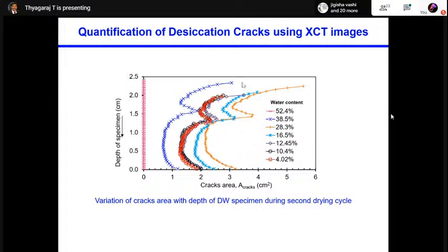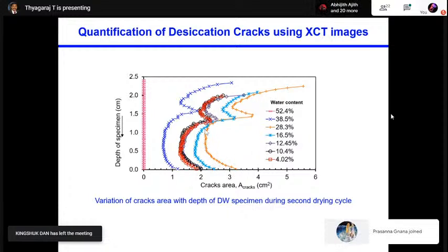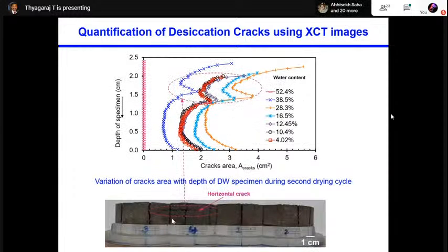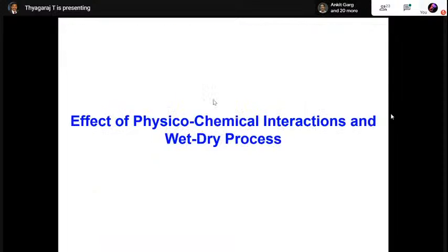Further, you can see that with the depth variation, at the surface cracks were more and at the bottom cracks were more, but in the middle portion the cracks were reducing. And there is one small kink here where it suddenly increases because of the lateral crack that was formed at that depth. So that is because of this lateral crack that it has increased.